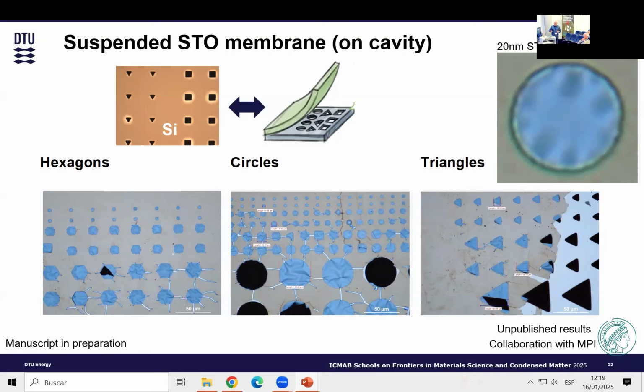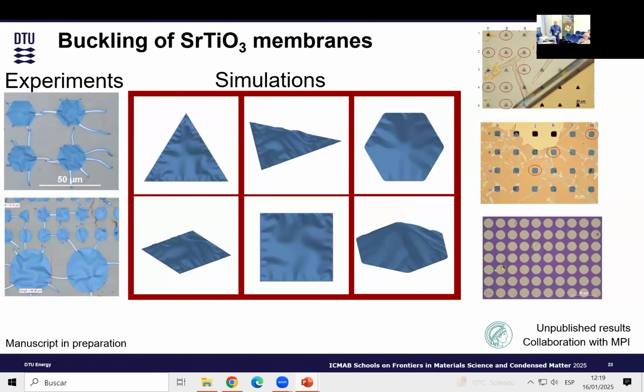This is the circular shape, and we also did simulation, and we could simulate exactly the same shapes as we observe in the membranes. Now, that was interesting. We observed something that we thought would happen, because there was no reason why not. What's interesting is that if you go to an even smaller size, less than 10 micrometers, we observe that the material becomes almost flat, regardless. So this is a membrane on top of this. You can see some defects here and here, but these are flat membranes. The same goes for the square and the triangle.